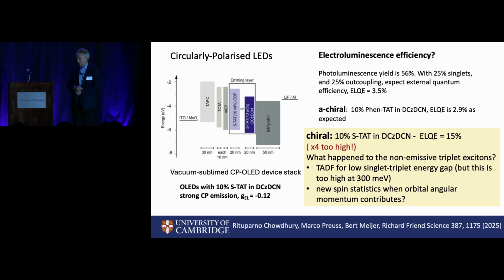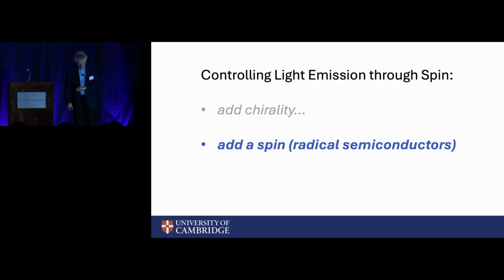Broadly, it looks as though when we've now got orbital angular momentum in the mix as well as spin momentum, we have an overall J, and within conservation of J, it turns out that everything is luminescent. And we found, rather surprisingly, it looks as though adding in chirality might have unlocked that problem of getting photons out irrespective of how the electron-hole capture takes place. So that was one. Let me carry on the journey.